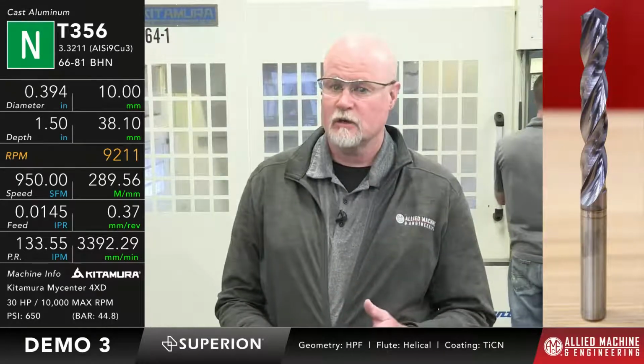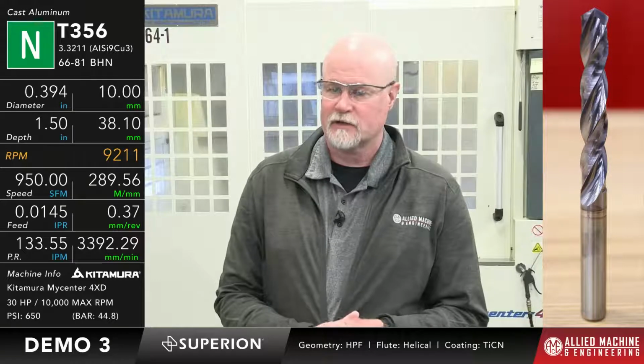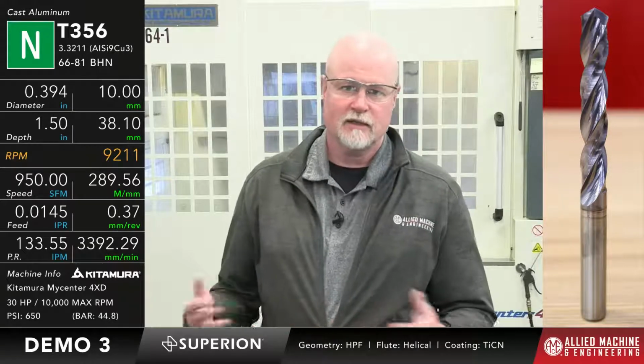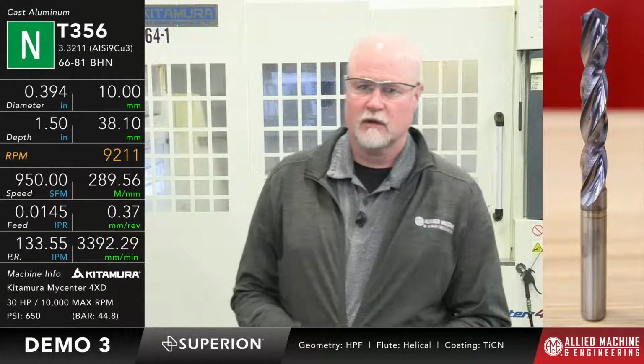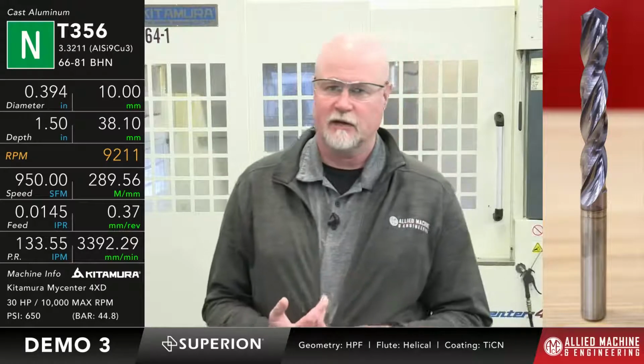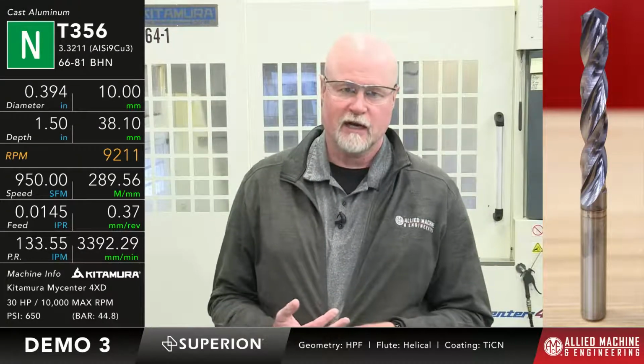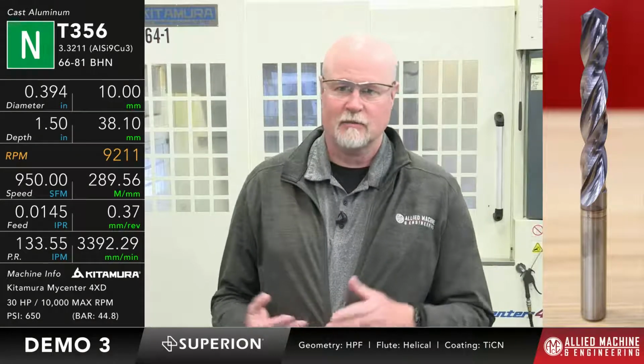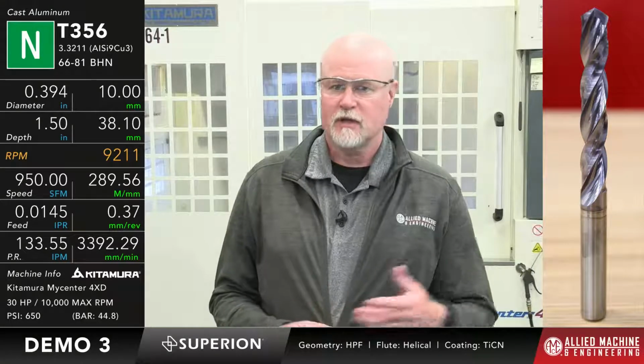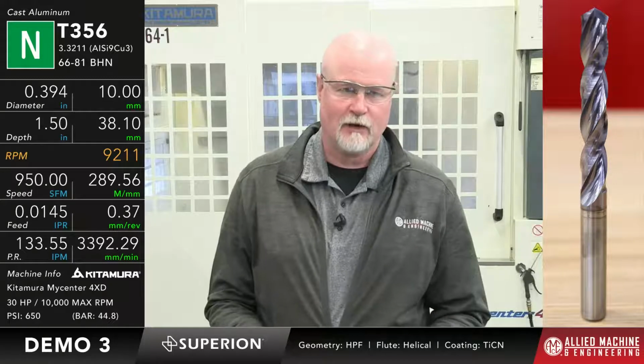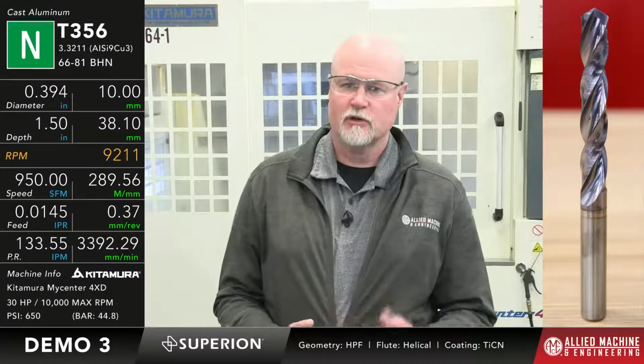So just to let you know what we're going to be running for this third demo, this material is T356, a cast aluminum, somewhere around 70 Brinell in hardness. Once again, we're still doing a 10 millimeter diameter, which is 0.394 inch, an inch and a half deep or 38.1 millimeters deep, speed of 950 surface feet per minute, 14.5 thou per rev, which in metric is 289 meters a minute and 0.37 millimeters per rev.